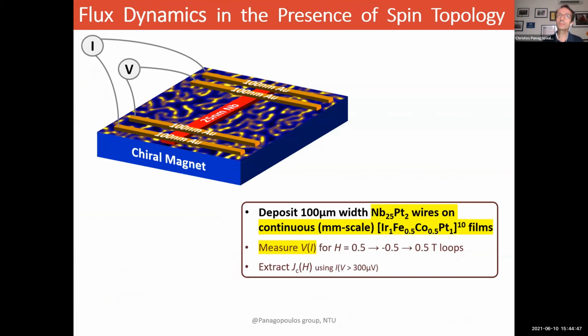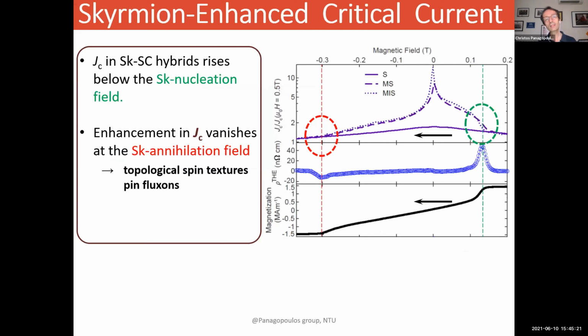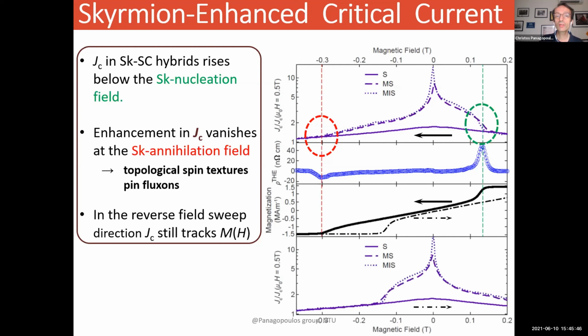So, having confirmed that we indeed have created skyrmions in superconductors and superconducting antivortices being connected, we can look at the flux dynamics of the superconductor in the presence of these spin topological defects, so-called skyrmions. For this, we deposited niobium platinum wires on a very large millimeter-scale heterostructure with skyrmions and measured IV characteristics. And you find that the critical current density in my superconducting skyrmion hybrid rises below the skyrmion nucleation field. This enhancement in the critical current density vanishes at the skyrmion annihilation field. So in other words, what this tells you is that these topological spin textures pin fluxons. And if you do the reverse field sweep, then the same holds true.